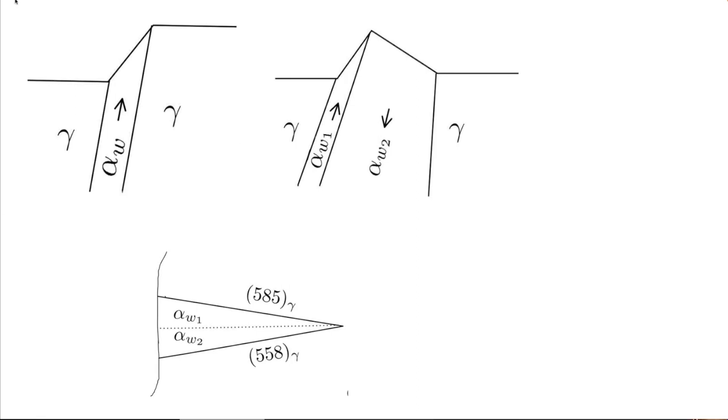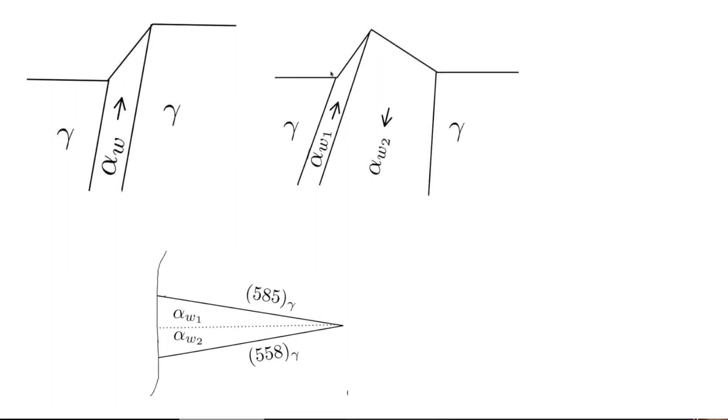Now, with a displacive transformation, this is the basic shape deformation that you should observe, a shear and a volume change normal to that. But what we are seeing is actually a displacement like this, where you have two plates growing together and accommodating each other's shear deformation. And in this way, they minimize the strain energy associated with the transformation, okay? Because one plate compensates for the other plate. So what it means is that, you know, if you have a particular shape deformation and a particular habit plane, then you also have a particular variant of the orientation relationship.